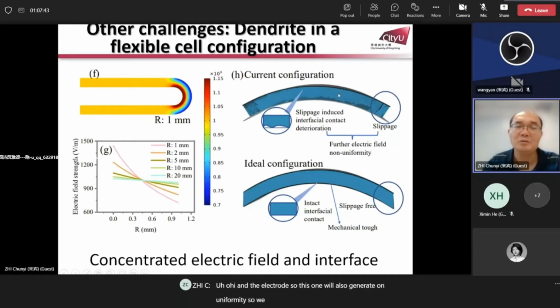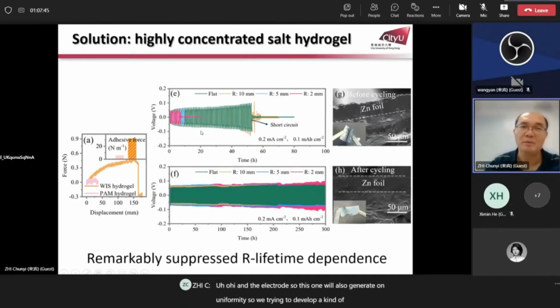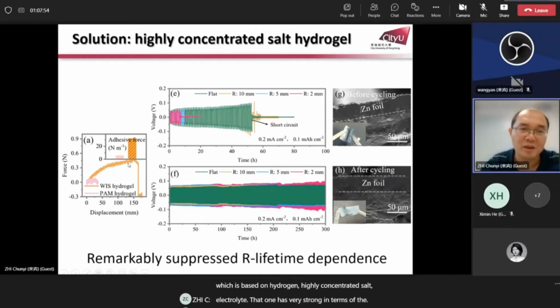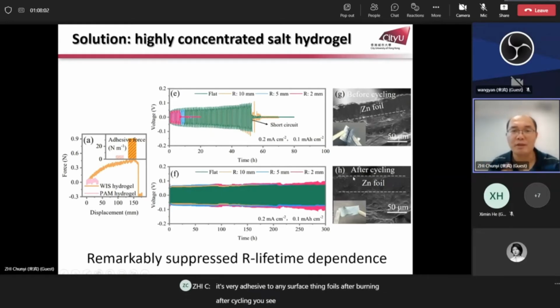So we are trying to develop a kind of hydrogel based on a highly concentrated salt electrolyte. That one is quite strong in terms of mechanical strength, and also very adhesive to any surface, such as zinc foils. After bending, after cycling, you see a very good interface.